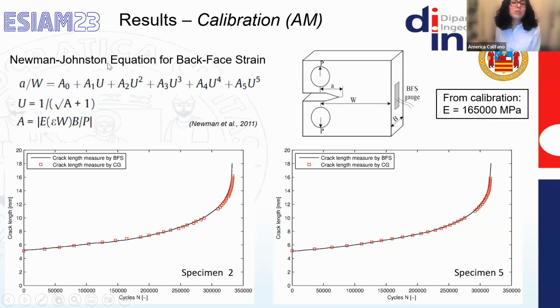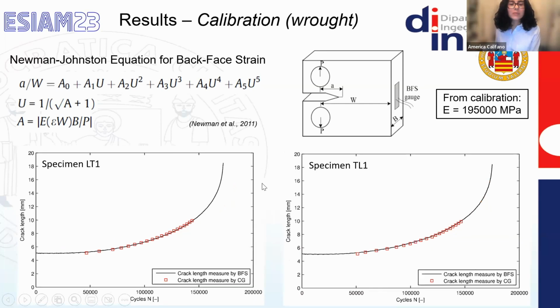In addition, the Newman-Johnston equation allows us to monitor the crack length against the number of cycles. The same procedure was carried out for the wrought material. In this case, a Young modulus of 195,000 megapascals was found. So there is a difference of about 30,000 megapascals between the Young modulus of the 2 materials. And again, here you can see in the 2 plots the curves of the crack length against the number of cycles for the LT1 and TL1 specimens.